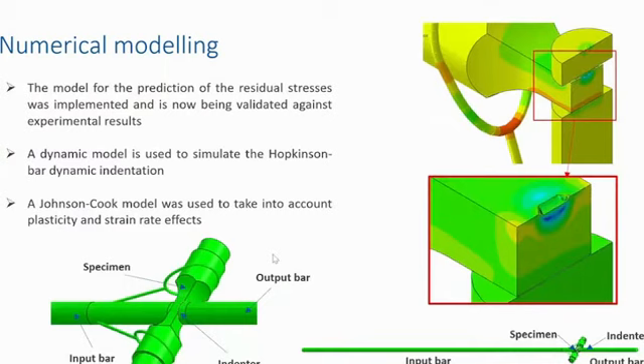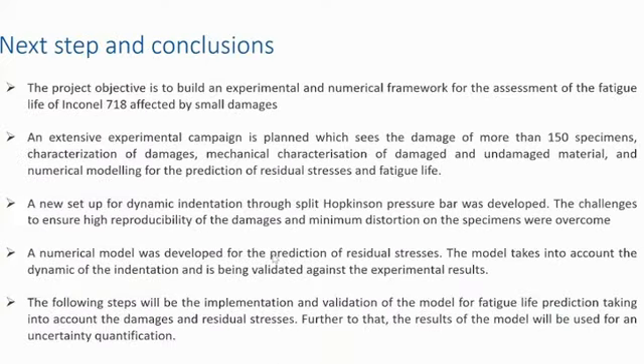Then we're implementing, we're validating a numerical model for the prediction of the residual stress, modeling all the setup of the Hopkinson bar with the input bar, specimen, indenter, output bar, and using elastoplastic material properties with strain dependency through a Johnson-Cook model. So in conclusion, we are working for the development of this experimental numerical procedure for the prediction of fatigue life in Inconel 718 affected by damages, and the final result should be the uncertainty quantification.